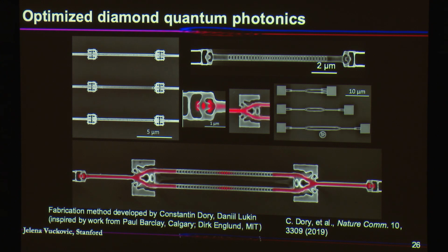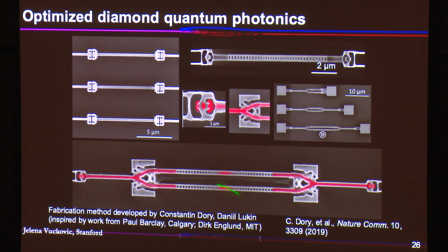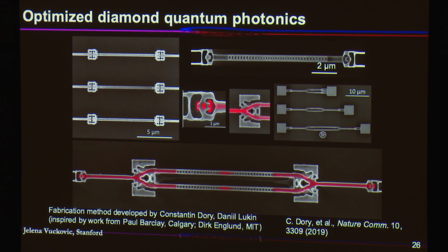In early work, we collaborated with a group of Marko Loncar at Harvard, who is my grad school friend. He's also a Caltech graduate, and he developed this technique for angled etching of diamond, which worked very nicely for cavities, but the structures that you make are pretty limited because you end up with a triangular cross-section. So we wanted to make more complicated circuits, and we adopted this approach of isotropic and anisotropic etching that was initially developed by Paul Barclay, who is also another Caltech graduate. He's now in Calgary. You basically etch down, protect the structure, then etch sideways. This method is now used by our group and also a group of my former PhD student, Dirk Englund at MIT, who also works on diamond. So we adopted the methods, changed them a little bit, and combined them with inverse design.